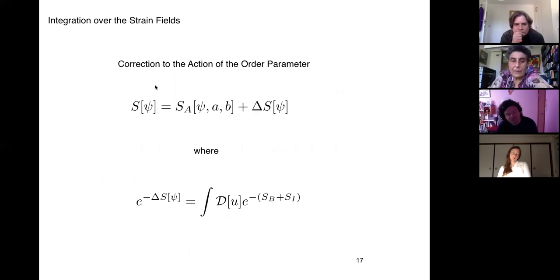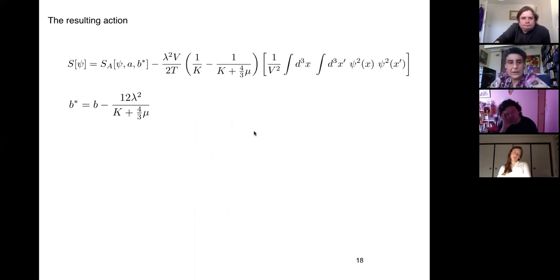The correction to the action of the order parameter, if we are interested in the effective action as a function of the order parameter, we can think of this as the original action of the system with clamped plus these other terms, where e to the minus S is going to be this integral. Here we're going to be integrating out all the terms in the action that have anything to do with the displacement. So this is what we get when we do all that. The resulting action will be S of A, the local term here, but with a renormalized short range interaction. And then we're going to have this other term.